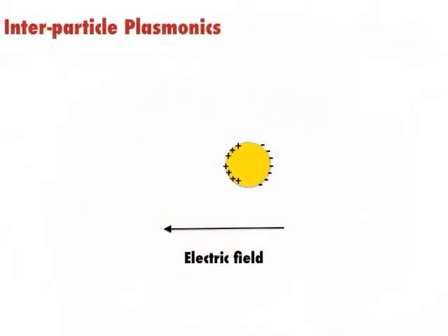Another type of transducer effect can be achieved when plasmonic nanoparticles are assembled into a network. Here, two nanoparticles are separated by distances on the order of 1 nanometer. Upon excitation, these particles undergo electromagnetic coupling in the near field, which concentrates the electromagnetic energy to the small volumes separating the nanoparticles. In this way, these assemblies can function as antennas that amplify optical signals or increase light absorption, which may be important for processes like solar energy conversion.